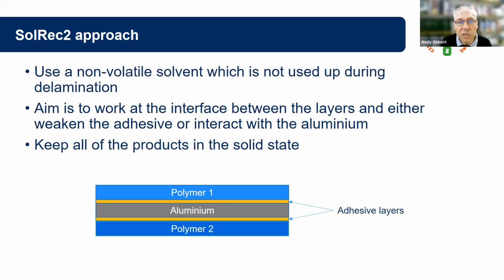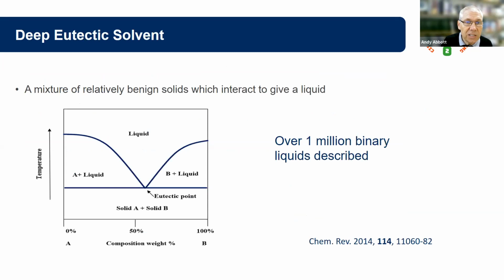And so what SOL-REC2 is trying to do is to use a non-volatile solvent, and that might sound like an oxymoron, but I'll show you in a minute that it's a very common way of using solvents. We're going to try to make sure that the solvent is not used up during the delamination process. What we're also trying to achieve is something that works at the interface, and particularly at that adhesive layer between the different polymers and metal layers. What we're trying to do here is not purposely dissolve anything, so not really have a solvent, but really to have something that softens the interfaces and gets us pure layers, which can be split later. So that's the dream, the ideal way in which this process would work. So the first thing we need to do is to get ourselves a solvent that is non-volatile.